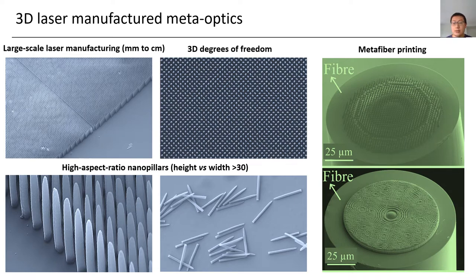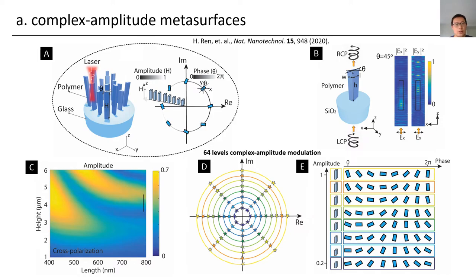Another big advantage that I would like to highlight using the 3D laser printing technology is you can put this metal surface on top of the fiber or any other flexible substrate, which is generally also difficult to achieve by the other planar lithography approach. So the first example I would like to highlight is the complex amplitude metasurface, where we can use the height of the nanopillar metal atom to control the amplitude, and simultaneously use the in-plane angle of this anisotropic nanopillar to control the geometric phase response. Altogether, we can end up with complex amplitude modulation.